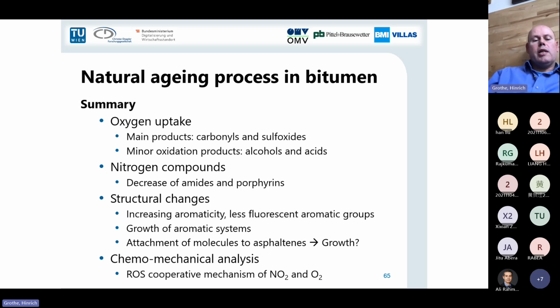We have structural changes. We have an increase in aromaticity. We have less fluorescent aromatic groups, as I have shown you, but we have a growth of the aromatic system. And probably they are attaching then to the asphaltenes. And eventually this explains also a little bit the difference between the NMR and the infrared result. And finally, we have a chemomechanical analysis, which shows us that the reactive oxygen species in a cooperative mechanism between nitrogen dioxide and molecular oxygen are mainly responsible for what we observe here as chemical aging.